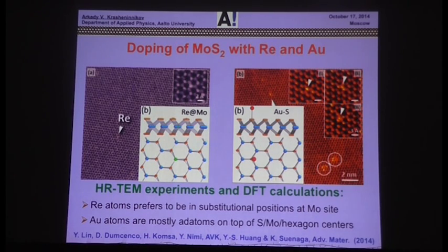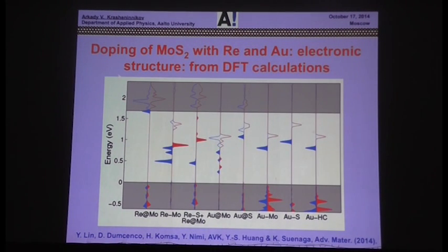As for electronic properties, rhenium has an extra electron, so it's obviously a very nice n-type donor. It gives a new state, a filled state, very close to the conduction band minimum. With gold, the situation is more complicated. But in general, when you get a small cluster, you may get p-type doping, contrary to rhenium, which gives rise to n-type doping.